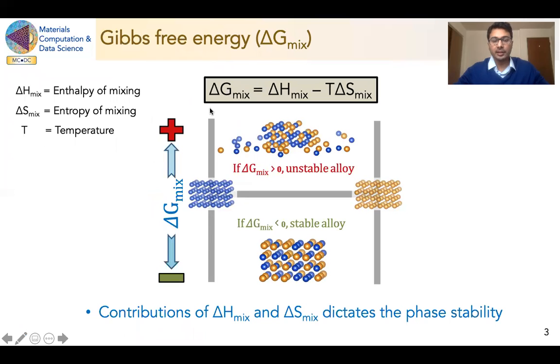Gibbs free energy dictates the phase stability of any alloy. And Gibbs free energy consists of two terms: enthalpy of mixing, delta H mix, and entropy of mixing, delta S mix. In this schematic, I am showing the concept of phase stability. The negative Gibbs free energy corresponds to stability of the alloy, whereas positive Gibbs free energy leads to instability in the alloy.